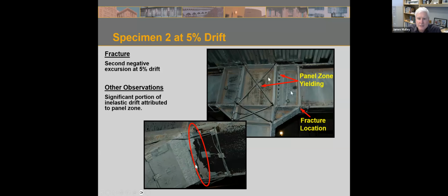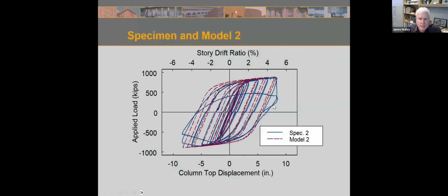So you can see still had some panel zone yielding in here, even though it was double haunch, and we did some finite element models on that later. But we did very much protect the existing brittle welds from fracture in this detail. Did a little finite element analysis, the test and the results, pretty close agreement, felt good about that.